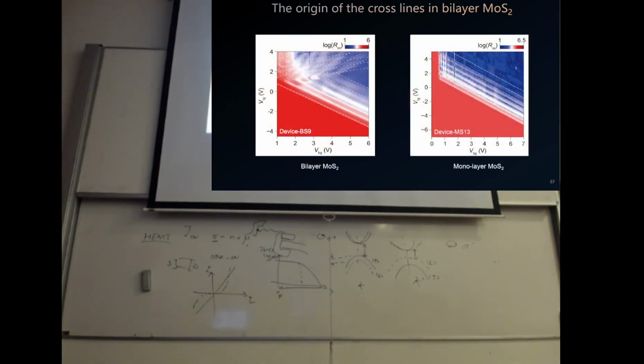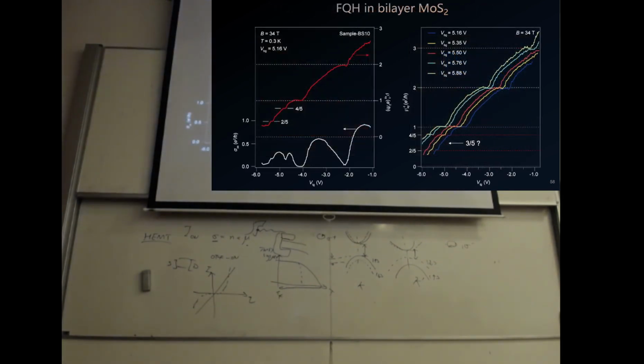Also, we can compare with the bilayer case and the monolayer case. In the monolayer case, we don't see these off-diagonal features as well. So everything is coherent, and if we put the system under 34 Tesla, which is rather high, and cool the system down to 0.3 Kelvin, you can even see fractionally quantized plateaus.